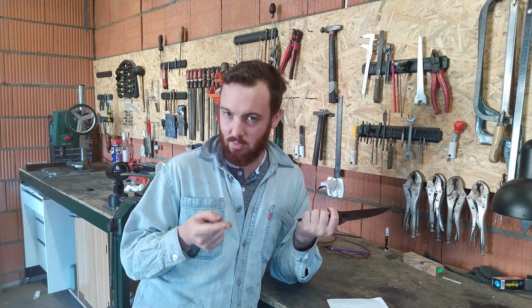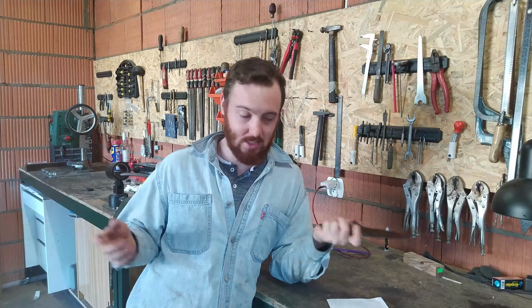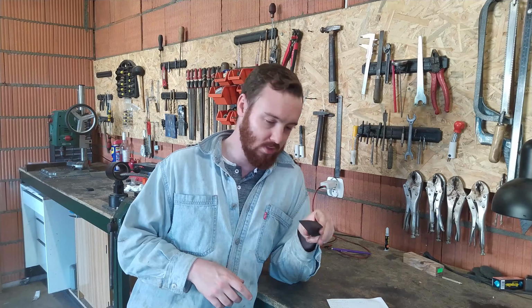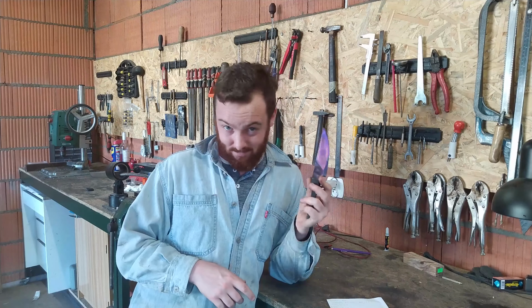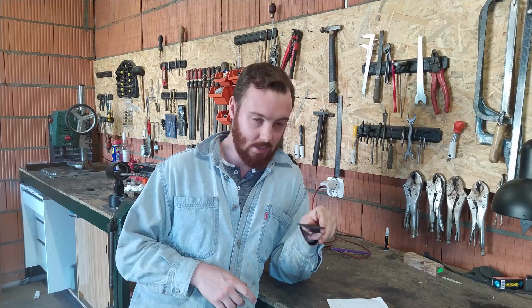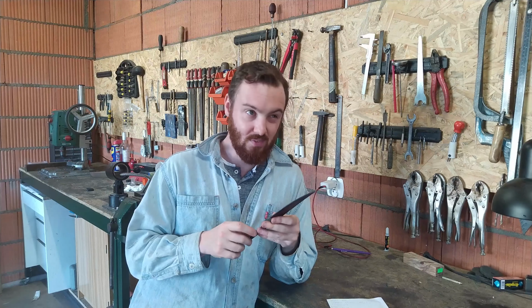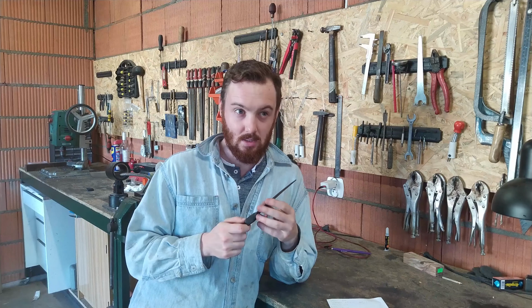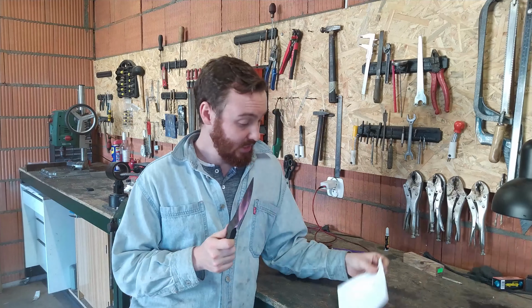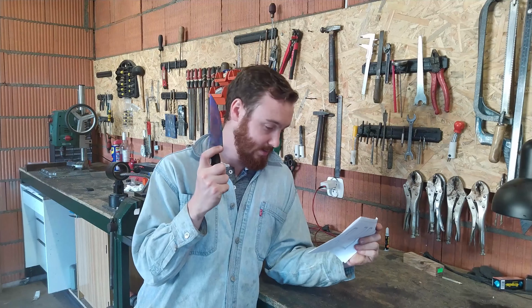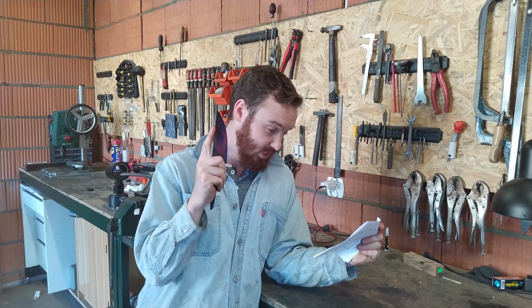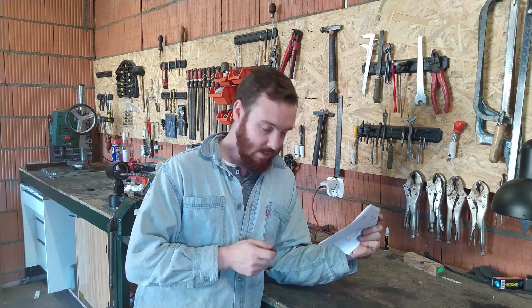After tempering, because I set the oven to 200 degrees Celsius, but it is super not accurate, so it probably was about 280. The color suggested it is blue and magenta, so it should be around 58, 57. In fact, on the tip it is 57, 58, depends on the place. Near the spine it is about 58, on the edge it is 57, on the middle is about 58,